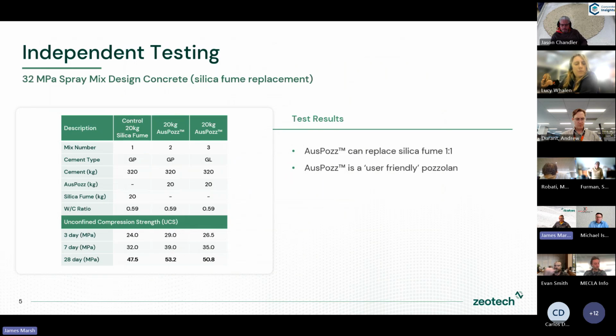I just dropped in a couple more slides. As it's a technical audience here, this is another one where we looked at directly replacing silica fume, because quite a lot of people would like to replace silica fume if they could, but usually you do lose some strength or lose other properties. Well, we just did a strength test here for a 32 MPa spray mix, a shotcrete mix. So we just dropped out 20 kilos of silica fume, put in 20 kilos of AusPozz. And here we've got, again, the water cement ratio the same. And we actually got a higher strength. So not a large amount higher, not the jump we saw with the previous work, but it certainly was higher. So that was a good result.